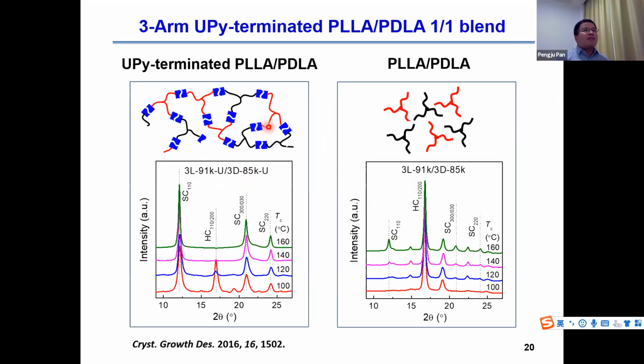Effect of UPy hydrogen bonding on crystalline structure becomes more significant for the polymer containing more UPy units. For example, for the PLLA and PDLA blend with 3 UPy units, they only form the stereocomplex crystal at a high crystallization temperature. The content of stereocomplex crystal is much higher than the common blend without the UPy hydrogen bonding. This means the stereocomplex crystallization ability can be enhanced by improving the interchain interaction.